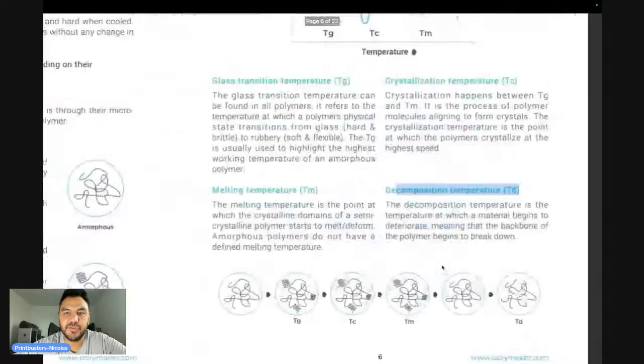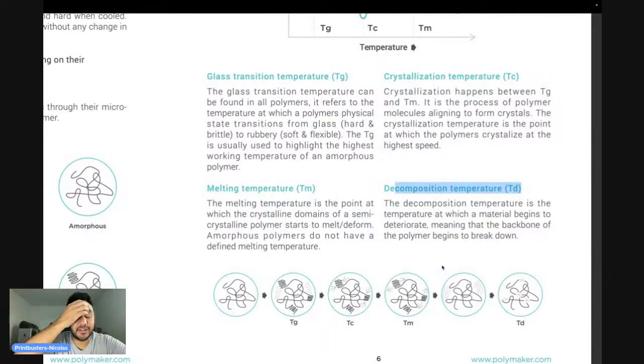So now when it comes to annealing, what's happening in annealing? When you anneal a semi-crystalline, you are creating these crystals, and the idea is that you want to reach the highest crystallinity degree of the polymer. What is the crystallinity degree? It's the ratio between the crystal area and the amorphous area. Let's say 50% of the polymer is crystals and 50% is amorphous. Then that 50% is the crystallinity degree. If it's 100%, then it's a complete crystal. And if it's 10%, then only 10% of the polymer has crystallized.